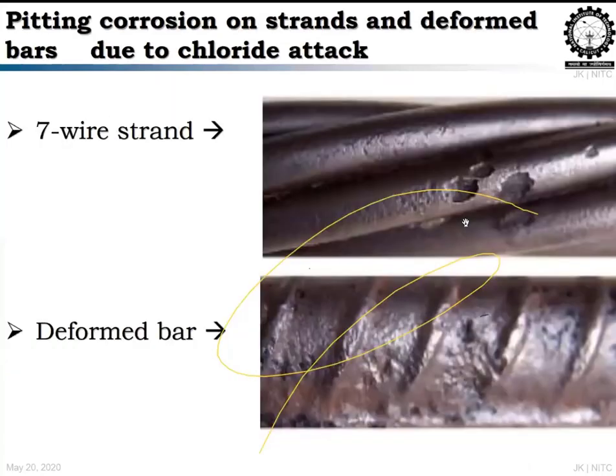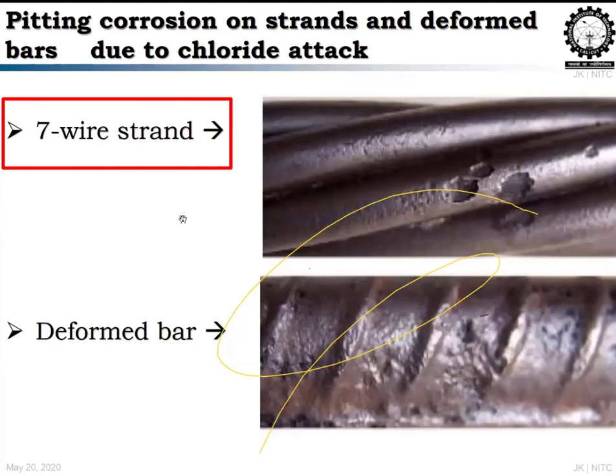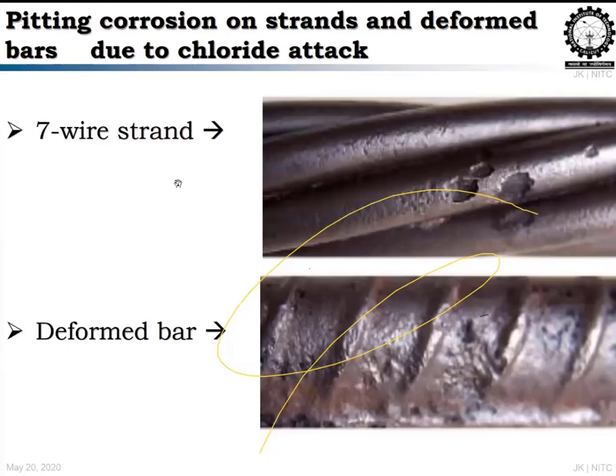Okay? And what is the major problem with that? One thing is, as you can see in the figures, a 7-wire strand which has pitting corrosion. That is the problem with chloride-induced corrosion. There you can see the pits. A pit forms a very small hole or indent over a very small area of the steel, which will go in depth and it will break. It will completely reduce the cross-sectional area of the steel, which cannot be detected by most of the NDT machines, whichever you are using for finding the cover depth, such as a rebar locator or profometer.